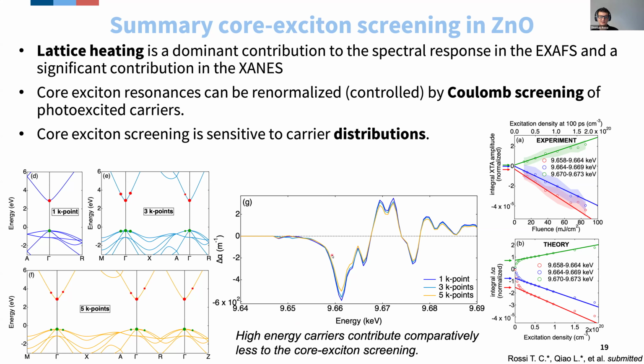And when you simulate the pump probe signal that's associated to that, what you find out is that there is a saturation of the amplitude of the signal. So when you put carriers further and further away from the high symmetry point, the pump probe signal that's associated to that is slightly less. And what this shows is that carriers that are actually further away from the high symmetry point comparatively contribute less to the Coulomb screening of core excitons than the ones that are at the high symmetry points. So this gives birth to this non-linearity. So the Coulomb screening is not only sensitive to the density of charge carriers, but it's also sensitive to their distribution in K-space.